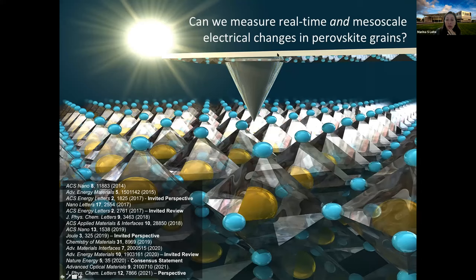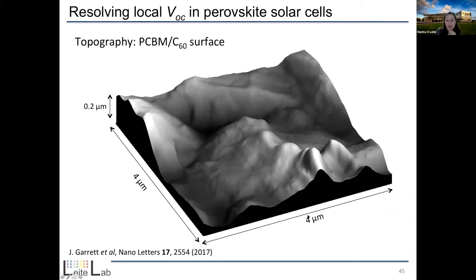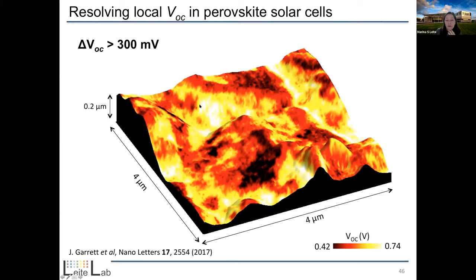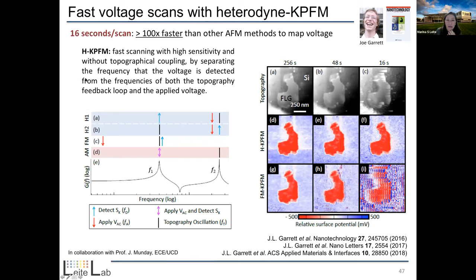Then we apply that scanning probe microscopy method that I mentioned to you. What we could do is, first of all, see that there was a lot of spatial variation in the local open circuit voltage, even within one grain, under 1 sun illumination. Then we were wondering what's causing that. It turns out scanning probe microscopy is very slow, right? You need a lot of patience to deal with that. But Joe Garrett was fantastic here, he essentially came up with a method that allowed us to scan the voltage locally more than 100 times faster. So every scan took only 16 seconds instead of the usual 25 minutes.